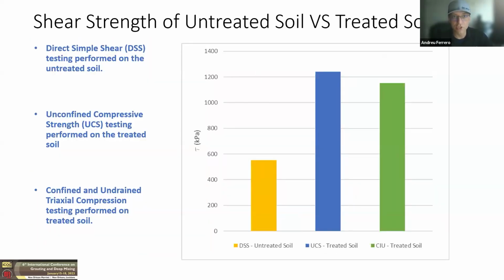Looking at the shear strengths of the untreated versus the treated soil, we took the direct simple shear values of shear strength for the untreated soil and compared that to the unconfined compressive strength shear values for the treated soil and the triaxial testing values for the treated soil. And we see that the UCS and the CIU triaxial test give us about the same shear strengths, which is a little more than double the untreated soil in the direct simple shear.